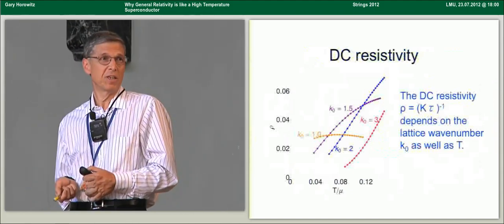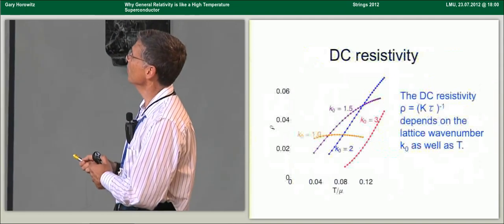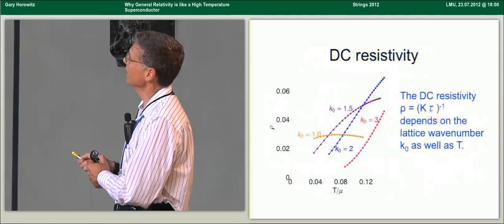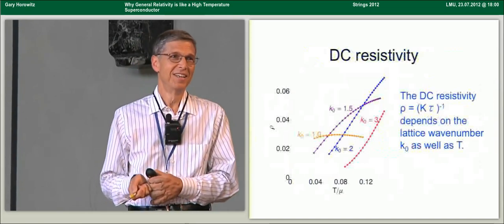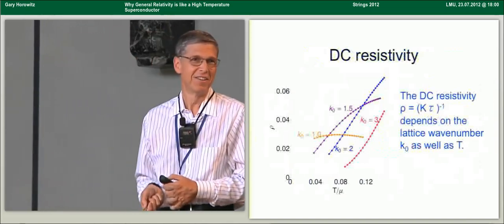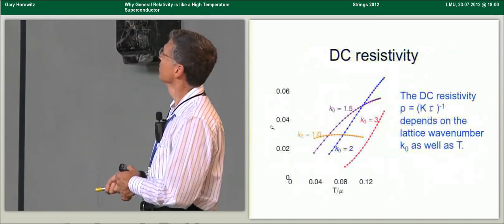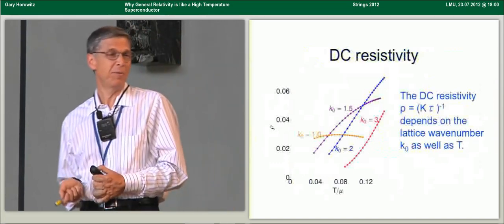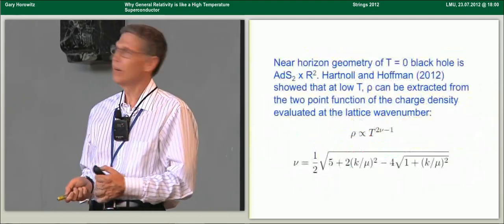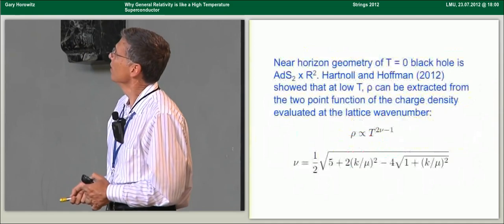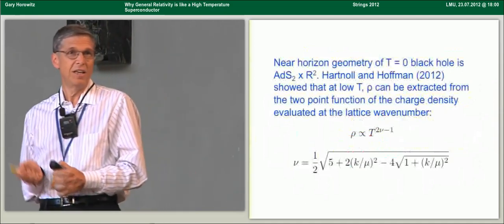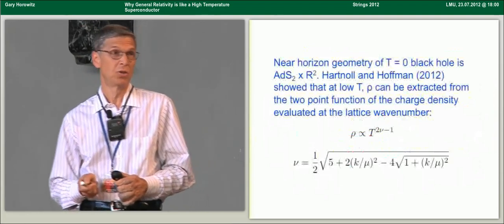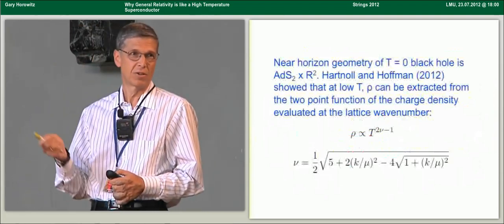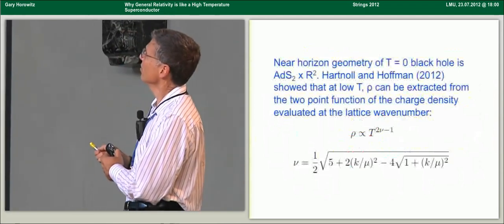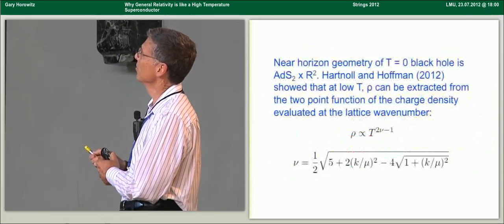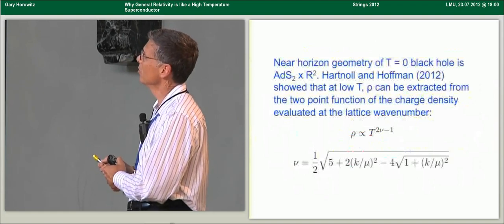Okay, when we first saw this, we were very confused. In fact, the first one we did was K0 equals 2. And we're actually very happy because that looked rather linear. And then we had the bad idea of checking other values of the lattice spacing, and we came up with this. But then we remembered there was a paper actually just a few months earlier by Hartnoll and Hoffman in which they studied the DC conductivity in the case when you had this locally critical region characterized by AdS2 cross R2. And Hartnoll and Hoffman showed that at low temperature, this DC resistivity can be extracted from the 2-point function